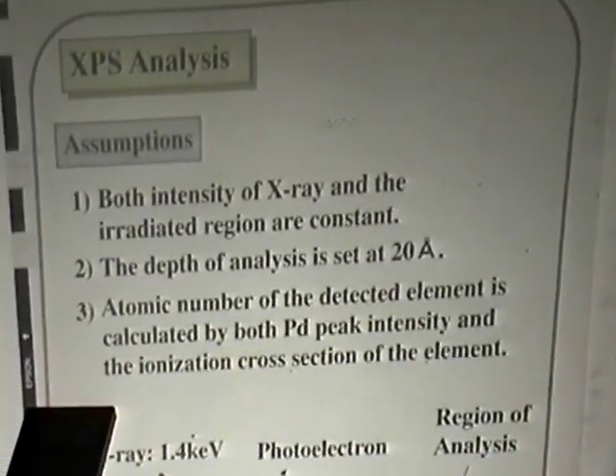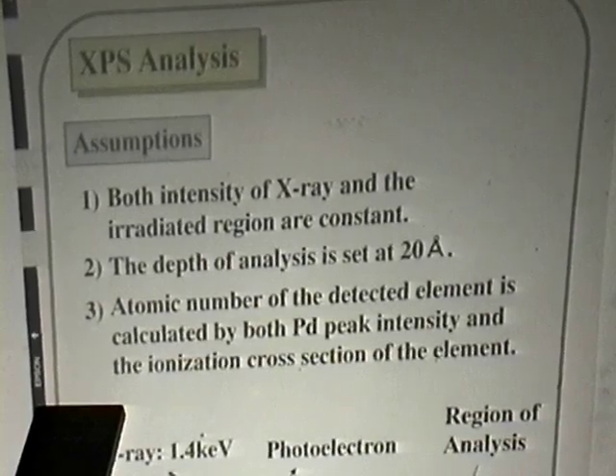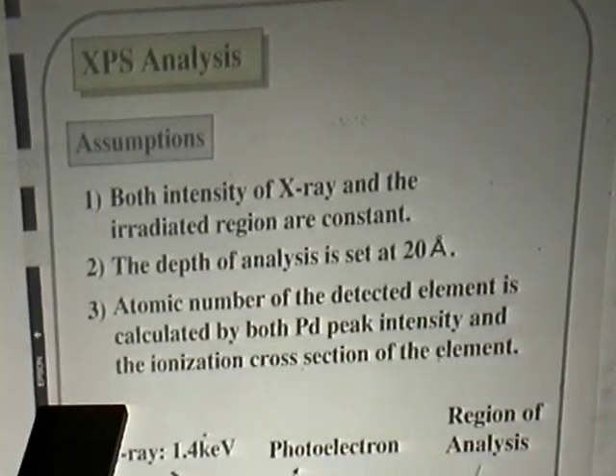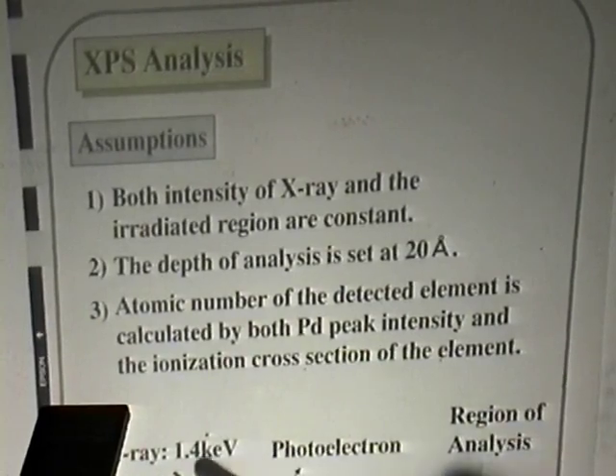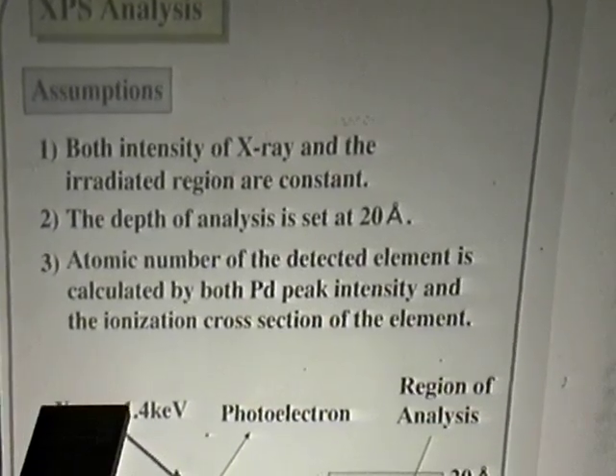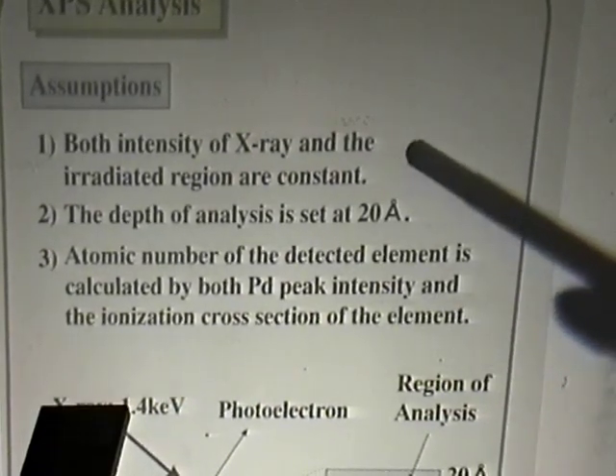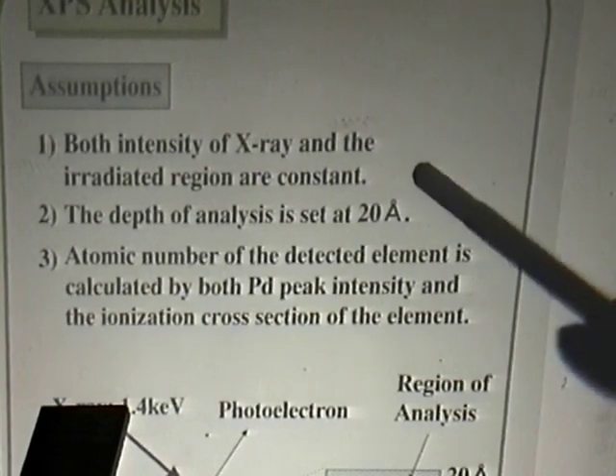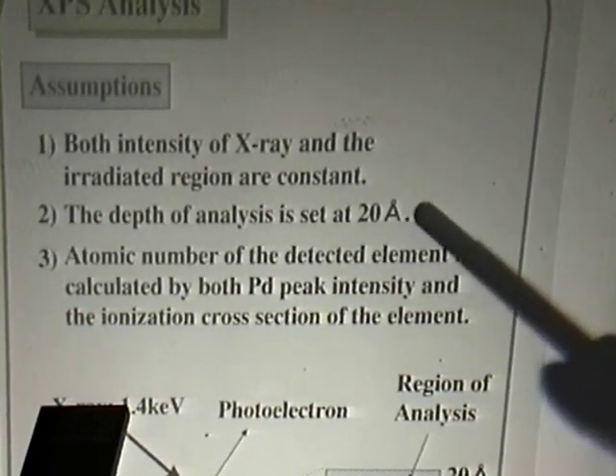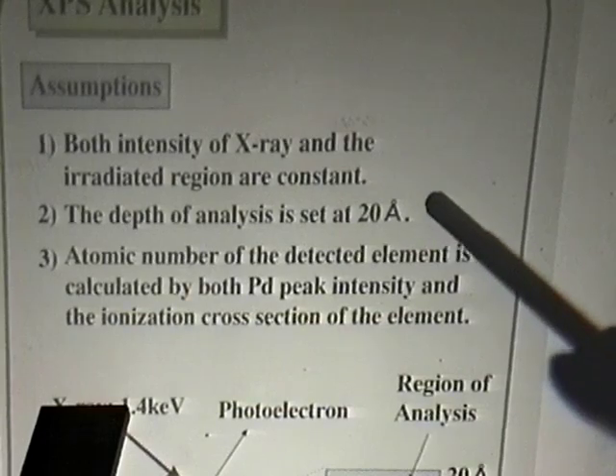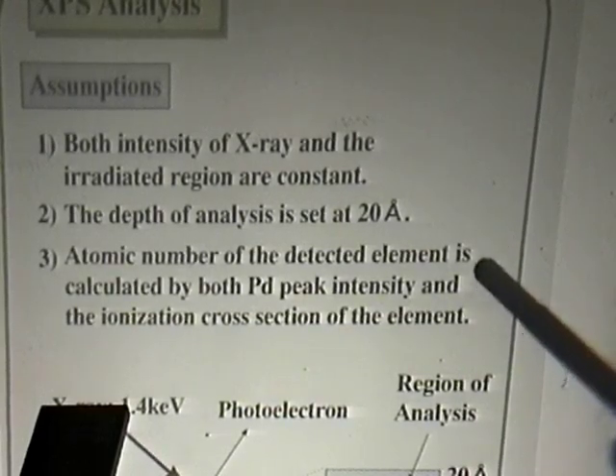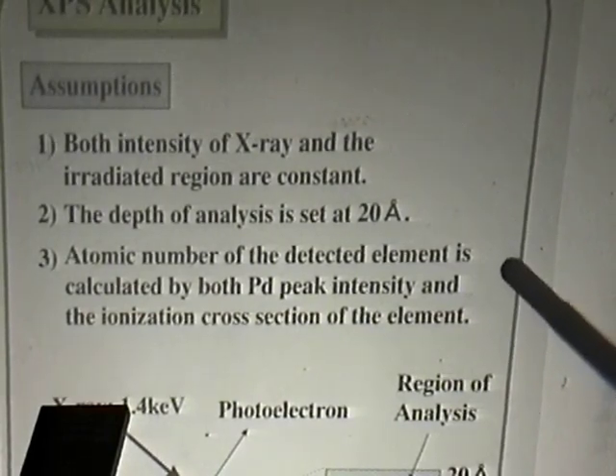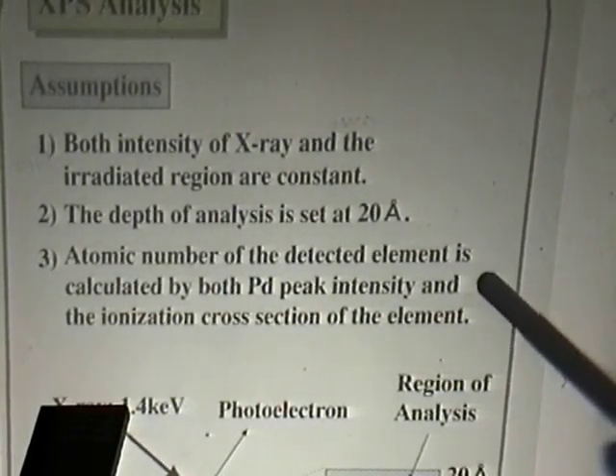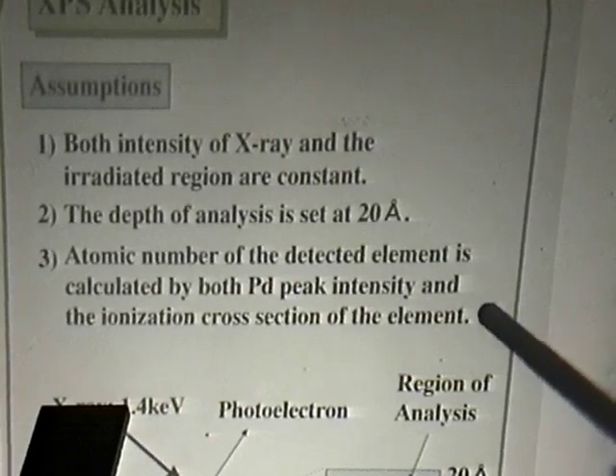XPS is a method of identifying elements by the energy analysis of photoelectrons, which are induced by X-ray irradiation, like this. Some assumptions of XPS analysis are given. Both the intensity of the X-ray and the irradiated region are constant. The depth of analysis is set at 20 angstrom. And third, the atomic number of the detected element is calculated by both the palladium peak intensity and the ionization cross-section of the element.